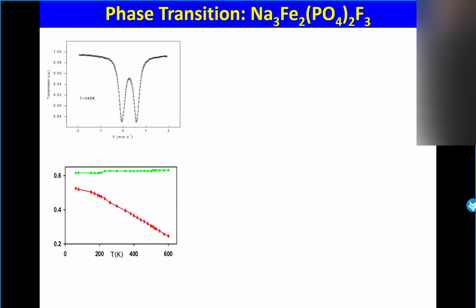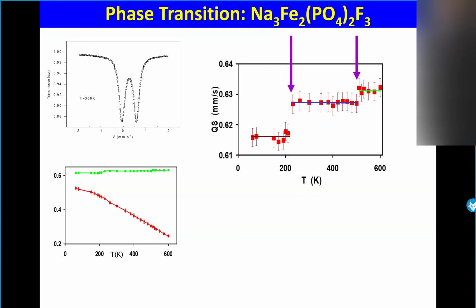Now the idea was to find a phase transition, because they were suspecting one. A phase transition means we have to do measurements versus temperature. We used the cryofurnace to perform measurements above and below room temperature, from 77K up to 600K. What we found, for the red curve, is the evolution of the isomer shift, which decreases as the temperature increases. And then the evolution of the quadrupolar splitting in the green one. No problem. But if we now look carefully at the green line, which is transformed into the red line, we can see two steps.